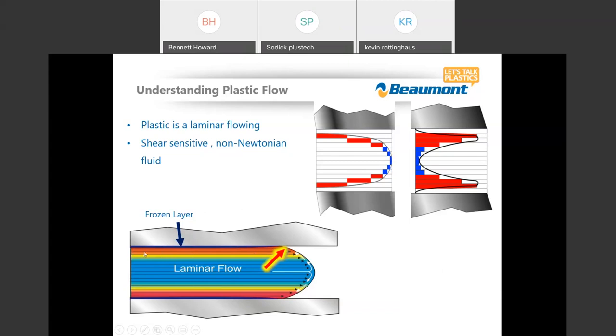If you can imagine putting your hands together and rubbing them real fast. We do that up here in the north, where I live in Wisconsin, in the wintertime, going from building to building to keep our hands warm. The same thing's happening with plastic flow, except on a completely different scale. We can create frictional heat and shear by rubbing our hands together. Think about what that shear rate must look like and how much higher temperatures we're seeing with a substance that takes a ton of energy and pressure to make it move. So we are experiencing very, very high shear rates and very elevated temperatures against this frozen layer.